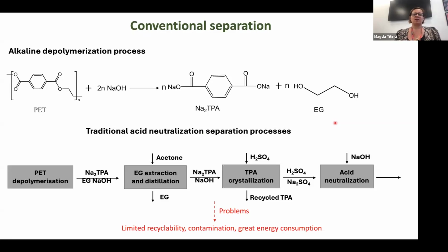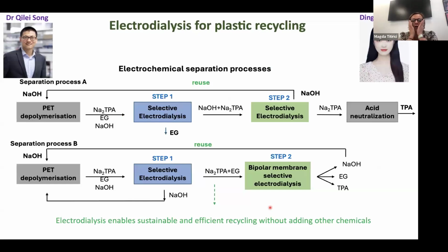Now, once we do the depolymerization, the conventional separation to get every component out of the mixture of sodium hydroxide, terephthalic acid, and ethylene glycol would be to extract ethylene glycol with acetone. Now you extract your ethylene glycol, and then you are left with a mixture of sodium terephthalate and sodium hydroxide. You add sulfuric acid to this, and you crystallize the terephthalic acid, and then you get sodium sulfate, to which you add sulfuric acid, and then you add again sodium hydroxide. So it's quite a complicated process. Now, we are overcoming the separation of all these components by doing this electrodialysis process.